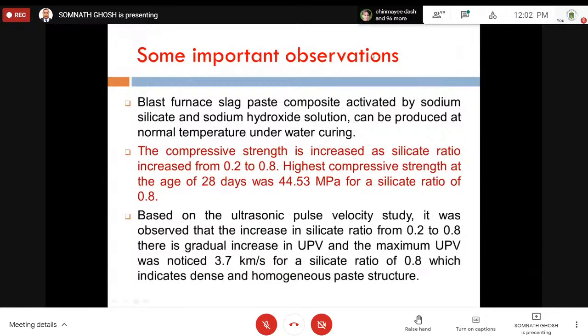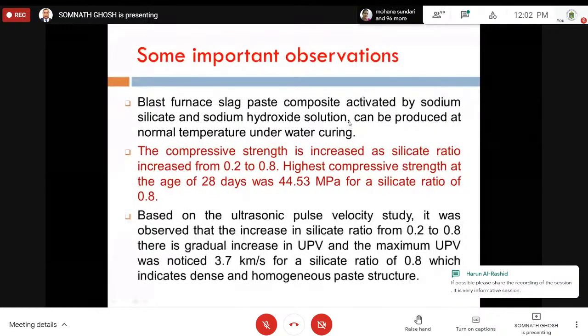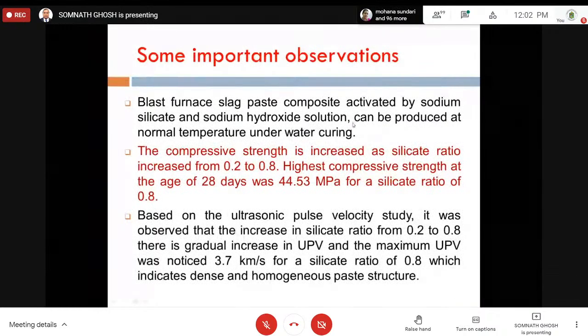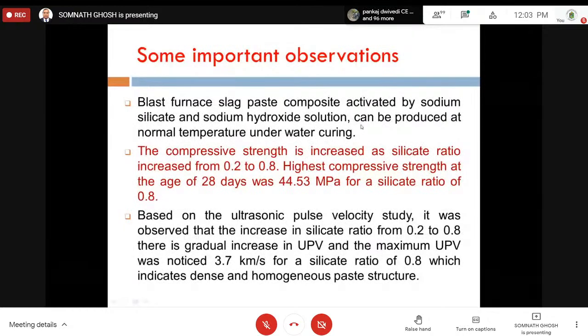You see, with some observations, I'll close the lecture today. This is the kind of observation we made in case of blast furnace slag. Blast furnace slag paste composite activated by sodium silicate and sodium hydroxide can be produced at normal temperatures under water curing. No heat curing is required. Now we have produced this alkali activated composite with slag and fly ash under water curing, because that is the demand of the industry. They don't want to go for heat curing because it consumes energy and cost is increased. They want water curing.